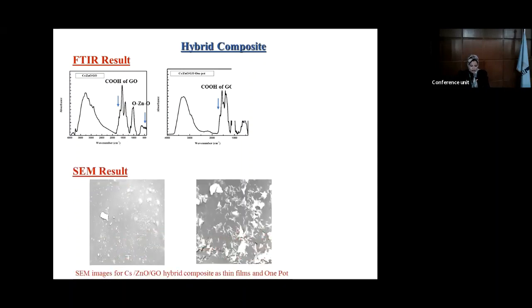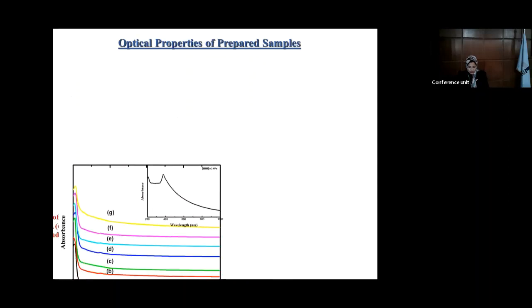The scanning image of chitosan, zinc oxide, graphene oxide prepared by casting revealed white spots that were distributed along the sample surface and accumulate in some areas. However, for the one-pot sample, there is a small white rod shape and other agglomerates on the chitosan surface, which indicates that there are many interactions between the chitosan, zinc oxide and the graphene oxide edges.